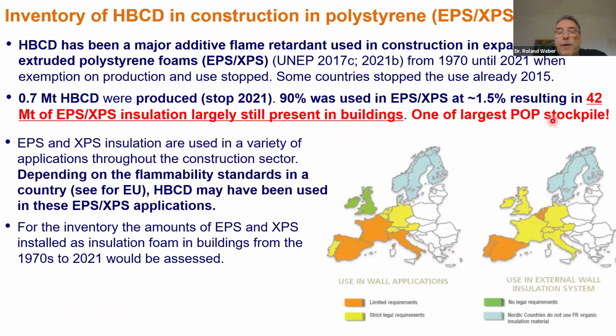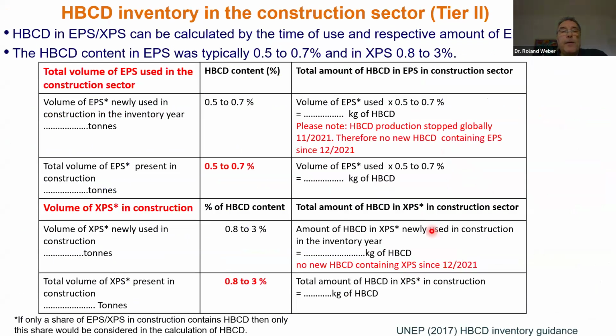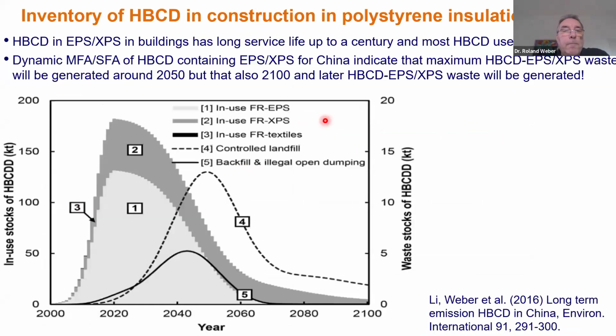But it depends a bit on the flammability standard. Not all countries have required the use of flame retardants in EPS and XPS. This is for Europe. When you do an inventory in your country, you first need to understand if flame retardants have been used and from what time on. We have an inventory guidance for HBCD, and this is a table there. So we know the concentration of HBCD. For example, in EPS it was between 0.5 and 0.7%, in XPS between 0.8 and 3%. If we know the total amount of EPS and XPS installed at the time of use, you can calculate how much EPS and XPS containing hexabromocyclododecane you have in your country.